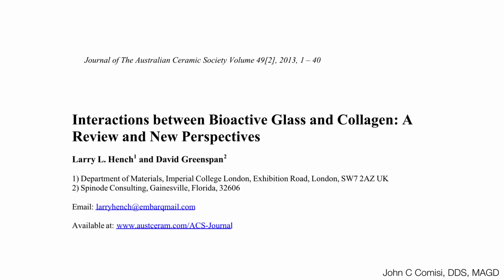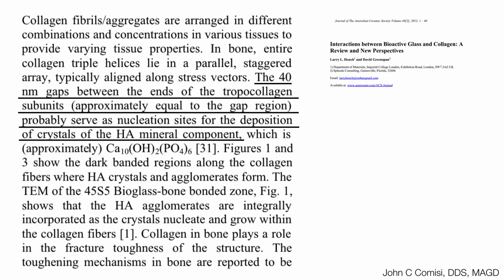Now, as I was doing some research, I found this paper by Hench and Greenspan published in 2013 on bioactive glass, which is another very big interest of mine, and collagen interaction. It pointed out something very interesting when I read it. It talks about this gap in the collagen fibrils. The gaps happen to be about 40 nanometers, which seem to give those sites the ability to create nucleation for the deposition of crystals of the hydroxyapatite mineral component, which was very interesting,